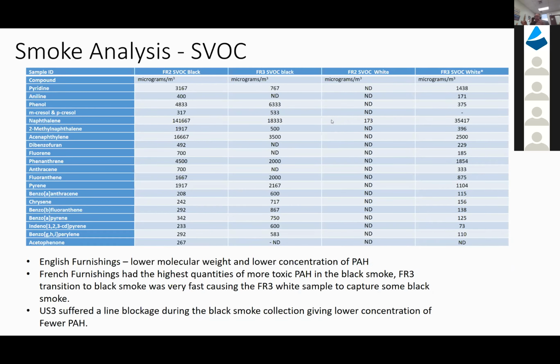So the bottom line is the English furnishings, the UK furnishings have lower molecular weight and lower concentrations of the PAHs, whereas the French furnishings had the highest, and the US was somewhere in between, but still very high. The black smoke is much more toxic and is produced much earlier for both the French furnishing and the US furnishing than for the UK. You have all that time to get out, so your exposure is going to be much less.